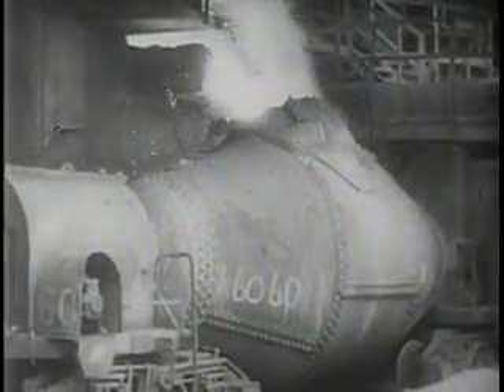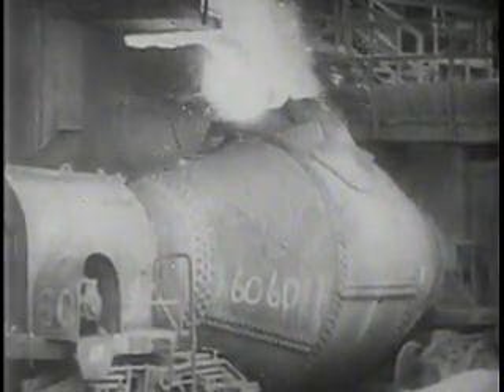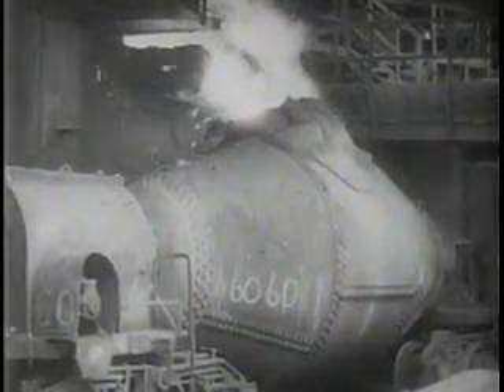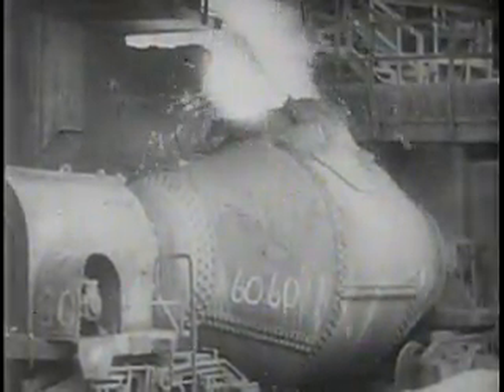Every 4 or 5 hours, the tapping hole is opened and out rushes a glowing stream of molten iron, termed in the industry hot metal. Sometimes this hot metal is poured into molds and the resulting pig iron shipped to foundries for castings. But usually the fiery river pours through channels which lead it over the tapping floor to huge ladles which hold 125 to 150 tons of hot metal.